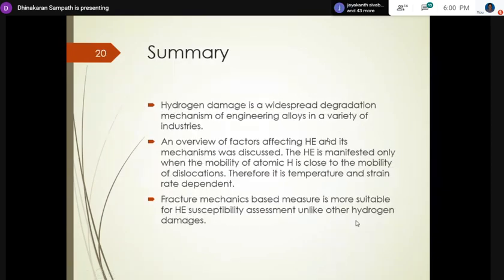So in summary, hydrogen damage is a widespread degradation mechanism of engineering alloys. We saw that it is seen in a wide variety of industries. And then the mechanism and the factors affecting hydrogen embrittlement. One key important thing to remember is that hydrogen embrittlement occurs only when the mobility of the hydrogen is very close to the mobility of dislocation.